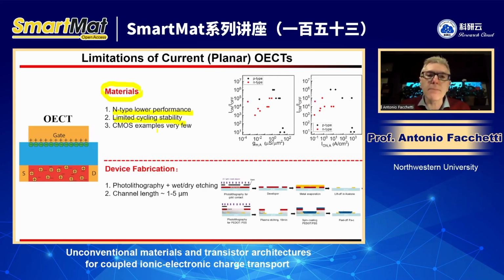There are very, very few examples of CMOS, and to do that you have to really use WL, which between the P and the N OECT is very, very different. So there is a challenge in device fabrication because you must use photolithography. For OTFT, you can have micron, 50 micron, 30 micron, you can use a shadow mask. But in OECT, the distance between the source and drain is on the order of 1 micron, 2 microns. So you cannot do it by thermal evaporation through a mask. So it remains challenging. So can we make devices which are easier to make, first question, and can we get good CMOS performance?